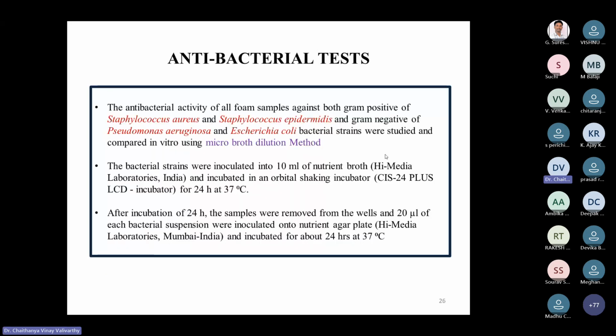Coming to antibacterial tests, the antibacterial activity of all foams was studied against both gram positive bacteria, S. aureus and S. epidermidis, and gram negative bacteria, P. aeruginosa and E. coli, compared in vitro using the microbroth dilution method. The bacterial strains were inoculated into 10 ml of nutrient broth and incubated in an orbital shaking incubator for 24 hours at 37 degrees Celsius. After incubation, 20 microliters of each bacterial suspension were inoculated on a nutrient agar plate and incubated again. Using these two positive and two negative bacteria, we get the antibacterial activity from the nutrient agar plates.